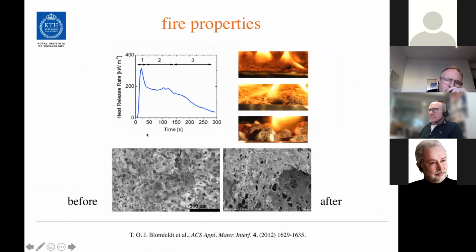One very interesting property with these proteins is that, as I mentioned before, they are much more fire resistant than polystyrene or polyurethane, for example. They also produce a large amount of char when they burn. So it's good properties if you consider making foam materials from this material. You can see the lower two pictures here show the foam material before a fire and after a fire. You essentially have the porous structures remaining even after a fire.